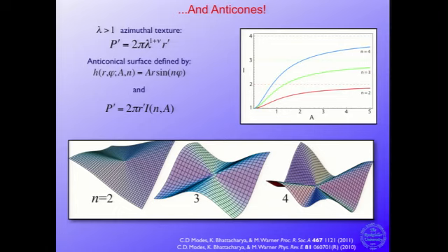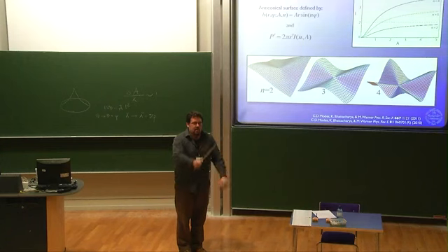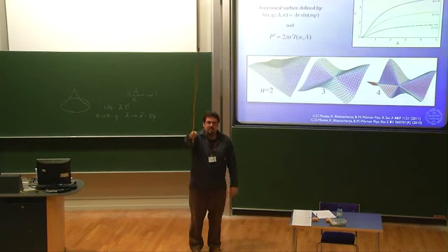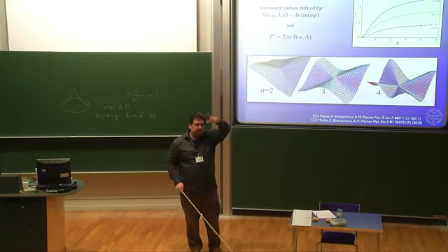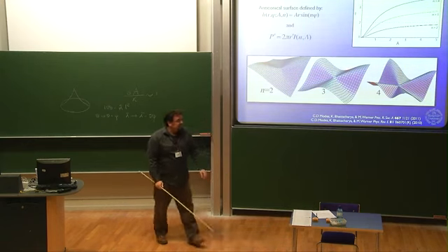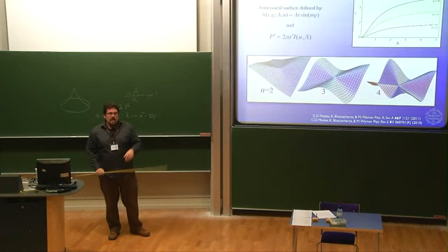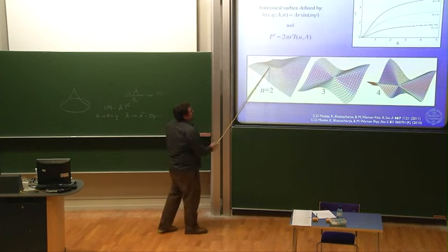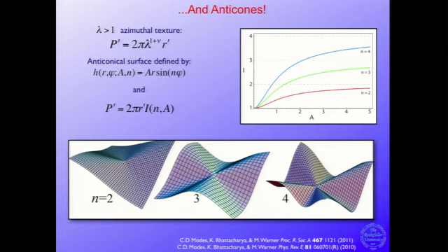You effectively get a modulation in the azimuth, but the generators of the shape are all straight lines. So if I were standing in the middle of the thing, the shape would just be up and then down and up and then back to where I started, with some number of nodes along the way. Because of that generation by the straight lines, you do get, in fact, that the Gaussian curvature everywhere off of the defected point in the center is 0.